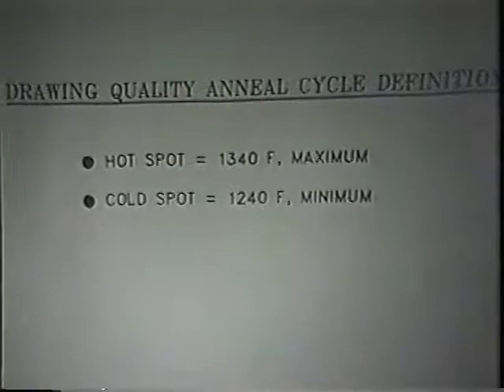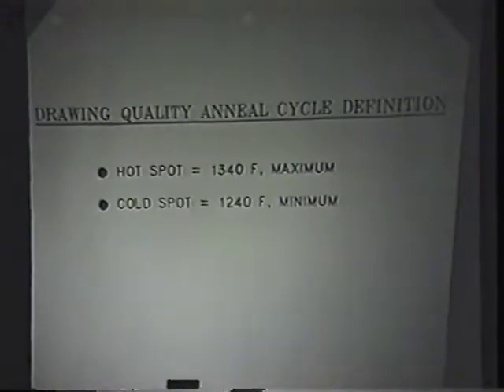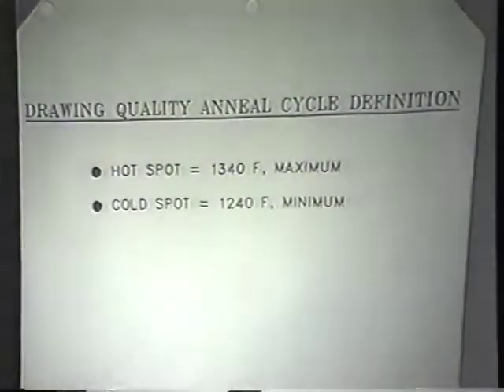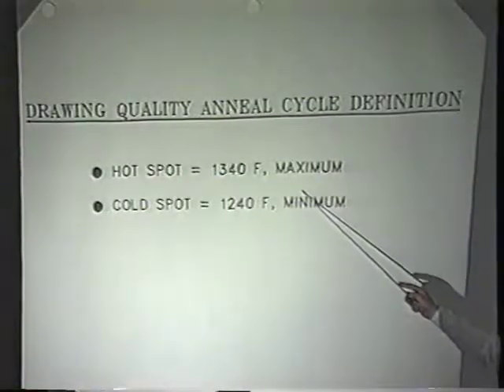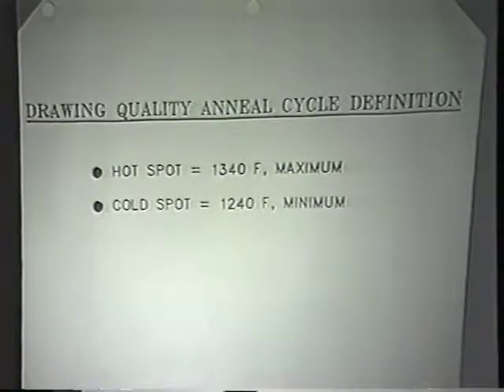Typically, a batch anneal cycle might look like this: 1240 to 1340. You've got 12 coils in that batch anneal for heat. Each one of them is going to get over 1240 degrees, every spot of the coil. And none of the portions of the coil are ever going to exceed 1340. What that means is you can have 100 degrees difference in that coil from front to back. That difference creates some temperature gradients, which creates some mechanical property gradients.